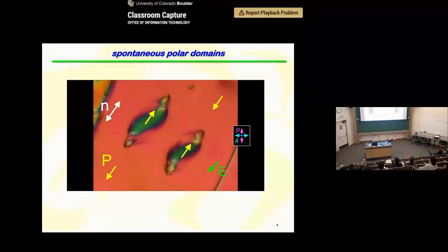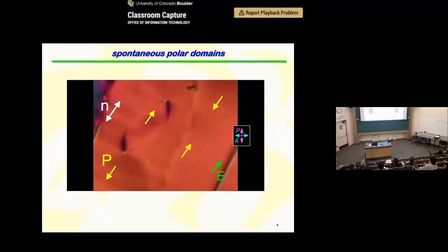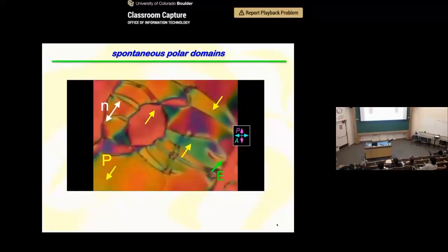So we apply an electric field pointing down, and the inside of these domains reorients. And this one goes away. When we switch the electric field going up, then this domain goes back to the original orientation and the outside reorients.